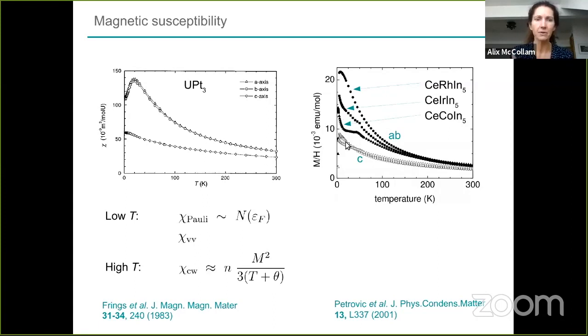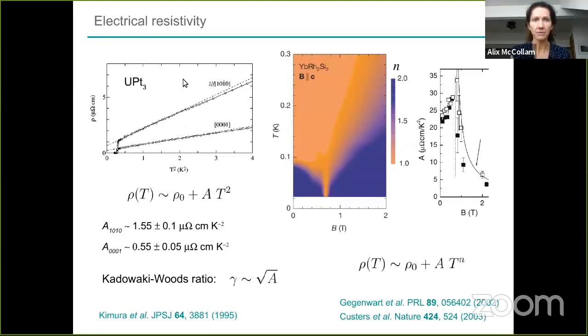So these are in different units, actually. So 120 here is about 10 here. So they're comparable sizes, just the units are slightly different. So they're typical magnetic susceptibility curves. This behavior, as I said, is not always predictable, but it's always large. Electrical resistivity is the other really important experimental quantity.